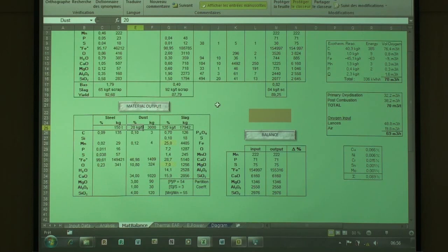No, DRI feeding not so much because you have a lot of fines. For short arc only. And if you elongate the arc, you create more dust. Typically nowadays the furnaces are all using UHP, so they are in a range of 18 to 22.